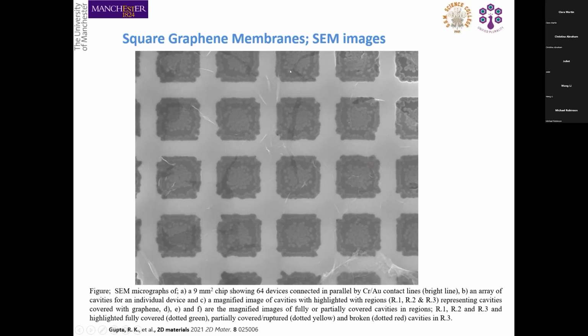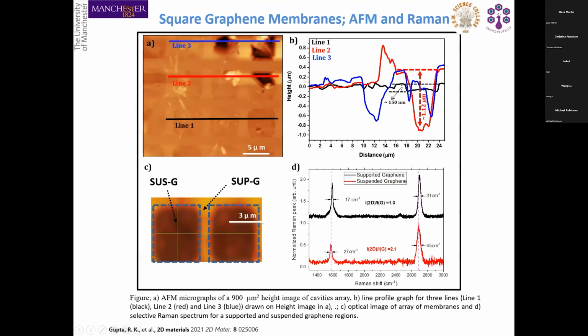So this is a 1 atom thick film, and it tears off at some point because all these things are done in a wet state. In a wet form, it always comes up with some sort of tear. And this also depends on the quality of graphene. So you can easily see this graphene film lying over the cavities.